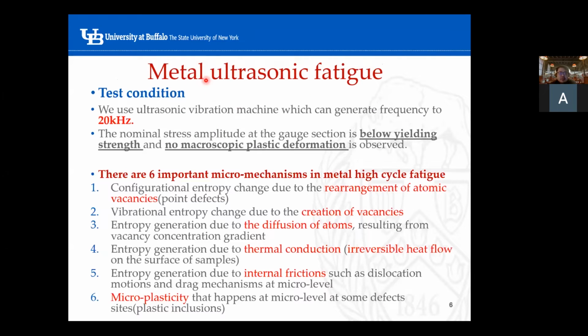For ultrasonic vibration fatigue of metal, the frequency is of course different than conventional tension compression hydraulic machines. We have a frequency around 20 kHz to 30 kHz. Under this high frequency, we will have a frequency effect and high strain rate effect that we have to consider in the entropy generation mechanisms.